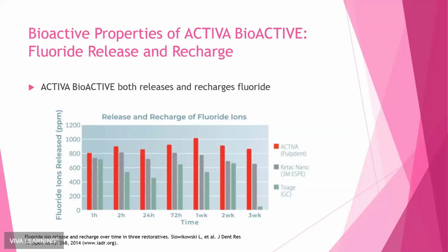This graph is showing you the fluoride release, but also the ability to recharge, of the Activa in comparison to the Ketac Nano and then the Triage. You can see we're looking at a period of 3 weeks here. So the area on the left is the first couple of hours to the first few days, and then we're looking at 1, 2, and 3 weeks. And you can see that not only is the Activa material starting with a higher amount of fluoride, but over a long period of time, it's really recharging and releasing a lot more fluoride than the competing products into that tooth structure. So if you're concerned about your patient's risk for caries or trying to prevent recurrent caries, putting a patient on a fluoride protocol in addition to using these materials can really benefit the patient in the long term.